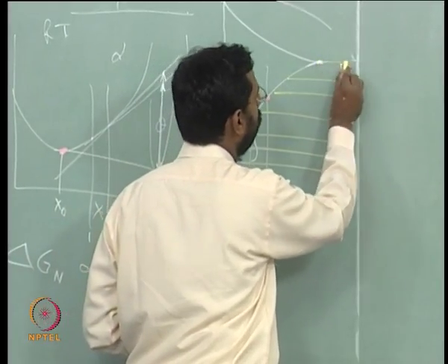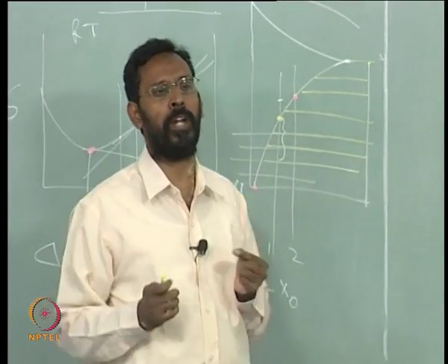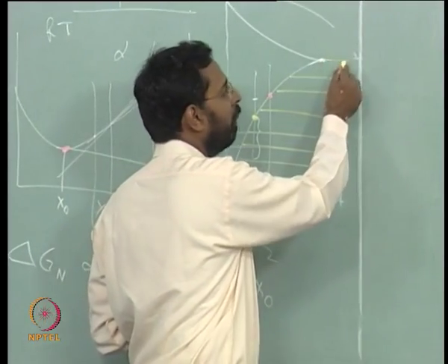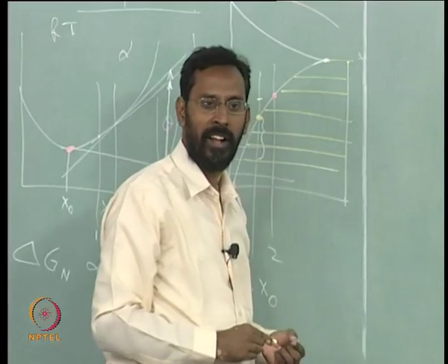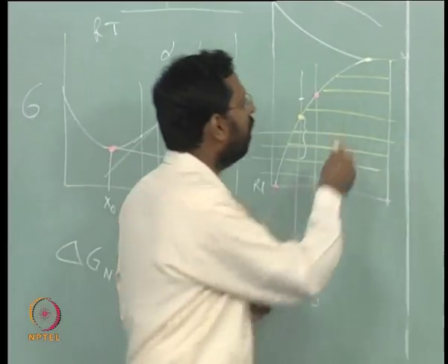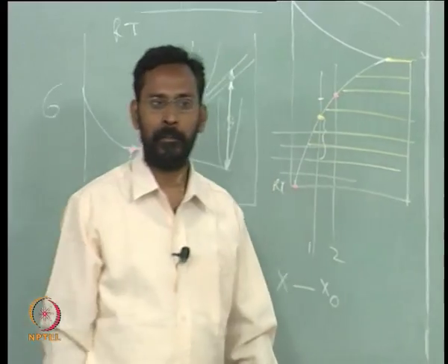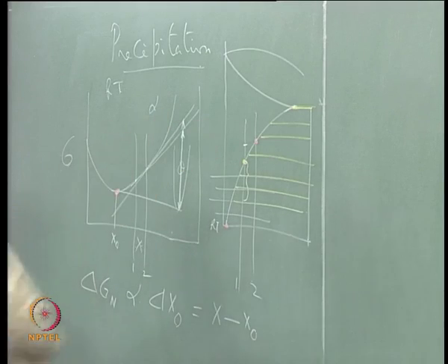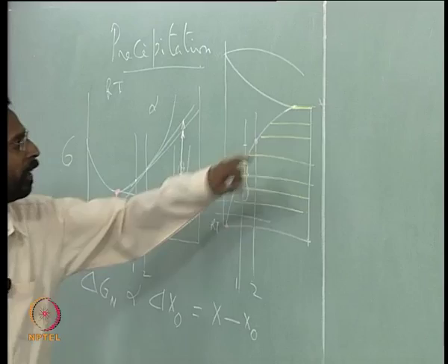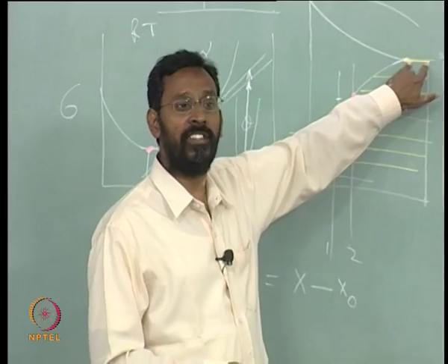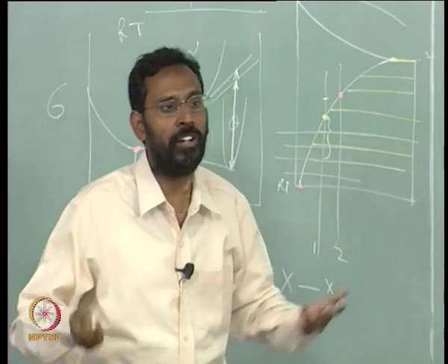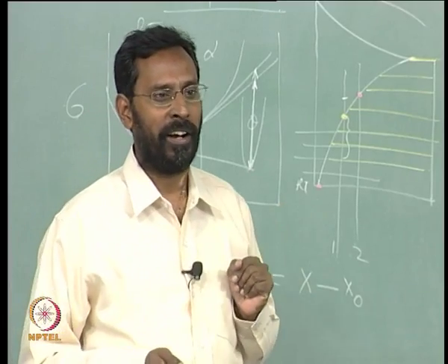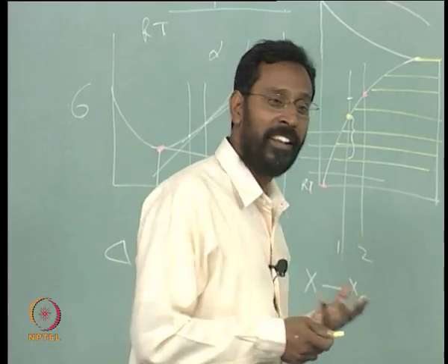at the eutectic temperature. Let us say you are just below the eutectic, melting has not yet started. Then you will see the alpha composition will be this, and you will still have some theta which is decided by this length of the line divided by the total from that to the theta phase, wherever the theta phase is, that is how we calculate. So this tells you that there is still some amount of theta, that means complete solutionizing has not happened, but still you can take such an alloy, and in such an alloy where is the theta?